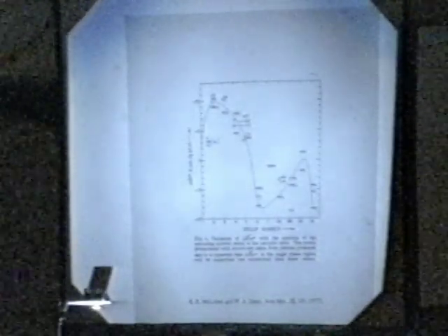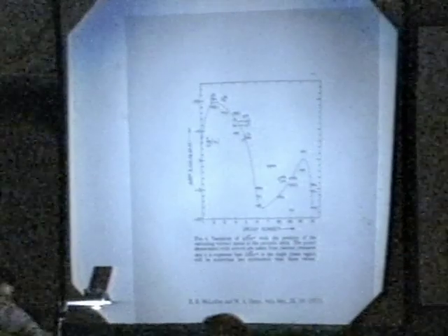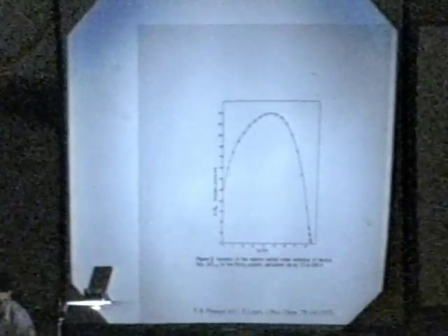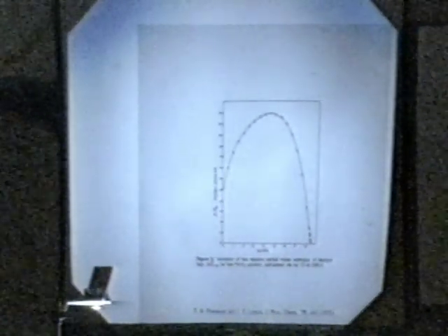What do we notice about palladium? Palladium stands out in this chart because although it's exothermic at infinite dilution, it's almost endothermic. In other words, it's not surprising that eventually the relative partial molar enthalpy should become endothermic. Notice nickel, by the way, which starts out endothermic. I have no idea what the significance of that is, but it emphasizes again, I think, the somewhat unusual properties of the palladium at infinite dilution. I just throw that out to your consideration.